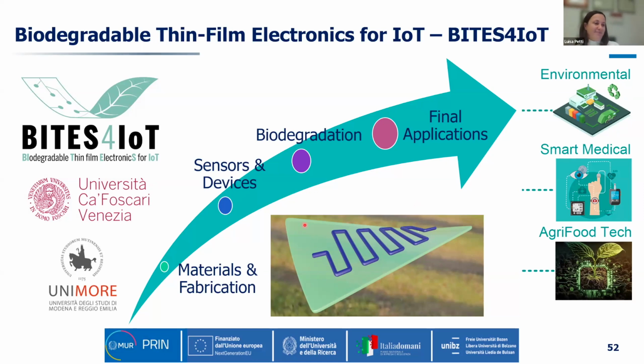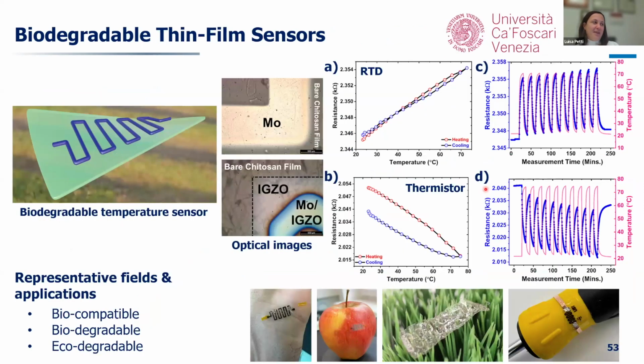We're not there yet, so what we worked a lot on is temperature sensors, an easy temperature sensor on a biodegradable chitosan substrate. Chitosan is extracted from crab skin. In Venice, they developed the process for chitosan. What we do is sputter. This is at the moment a completely dry sputtering process. We sputter through a shadow mask both resistive temperature detectors, RTDs, but also thermistors with an indium gallium zinc oxide semiconducting layer to develop temperature sensors that you see characterized here.